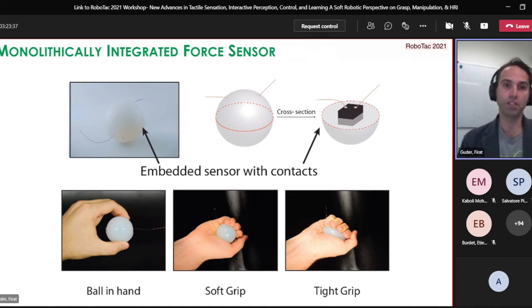So, for example, this is the sphere or the ball that I showed you earlier with that video. What you see here is a silicone ball, and inside we have a silicone-based material that's used as the sensor, and we also have silicone contacts. All these materials react together, and then we have a monolithically integrated, single-piece device. For example, if we were to put a PCB-based or thin film-based sensor that's not made of silicones inside this ball, then it would kind of move, because it wouldn't really bond with the silicone rubber. Here we have a really solid piece that acts as a single monolithic device.